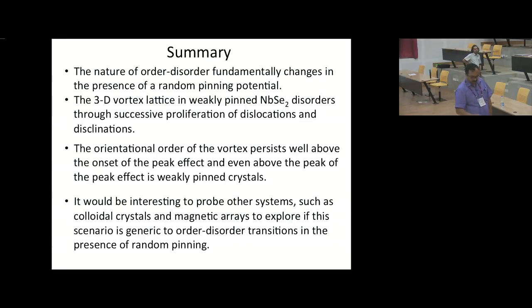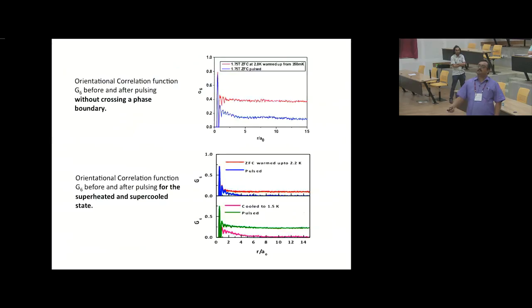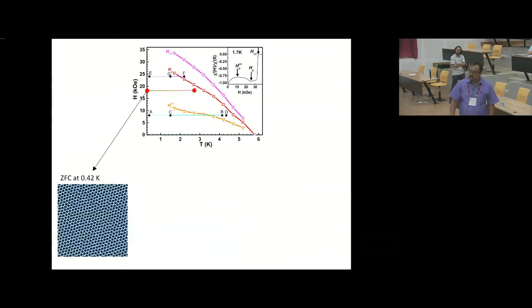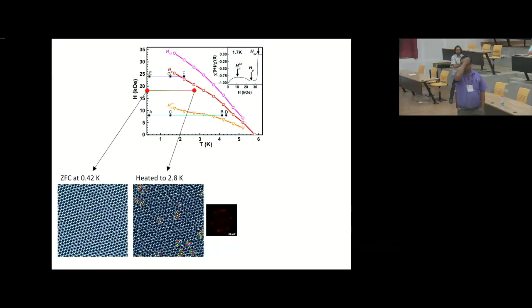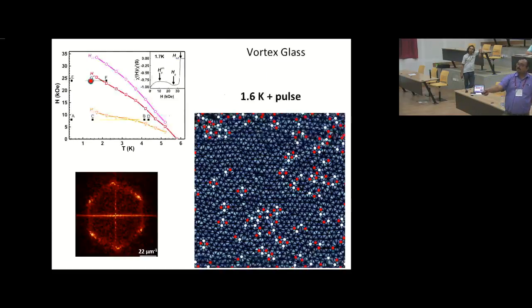The thing is, you are talking about this proliferation of dislocations and disclinations. I thought the standard thing is binding and unbinding, and many things that we're calling dislocation have four dots, red, white, red, white. Okay, that's possible. And there are some of them which are dislocation pairs also. And for first order melting, in terms of defects, there is this grain boundary, and many things look like a lining up of defects into a grain boundary. Here you don't see too many grain boundaries. In some of the images, for example, if you look at this image, I cannot really identify grain boundaries.